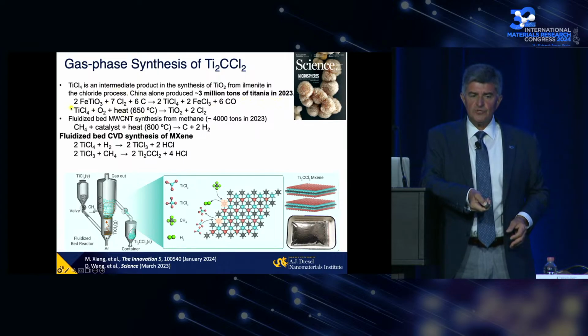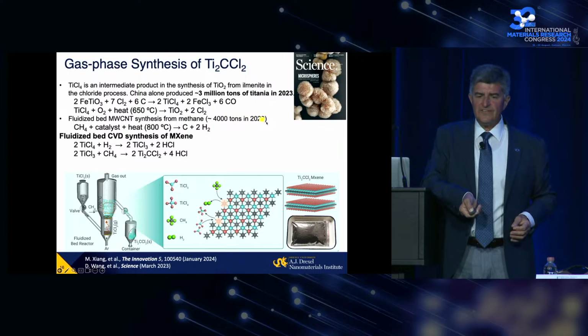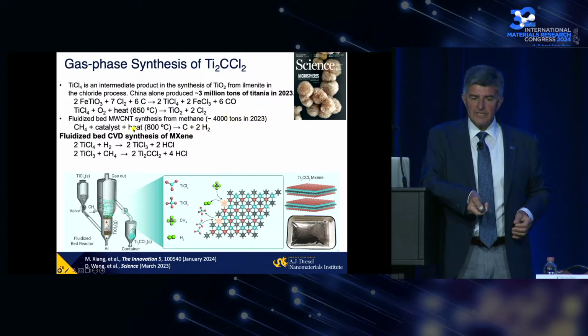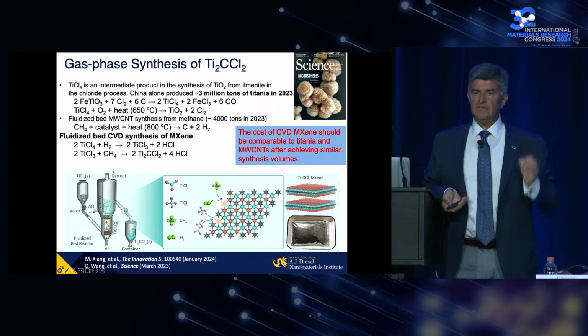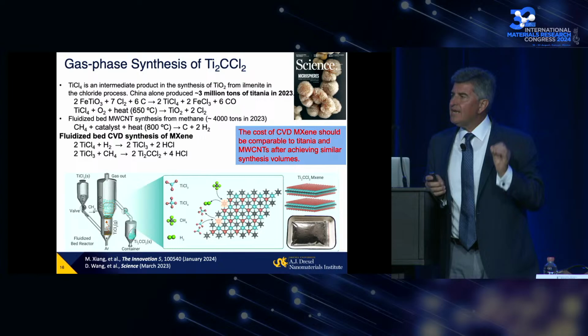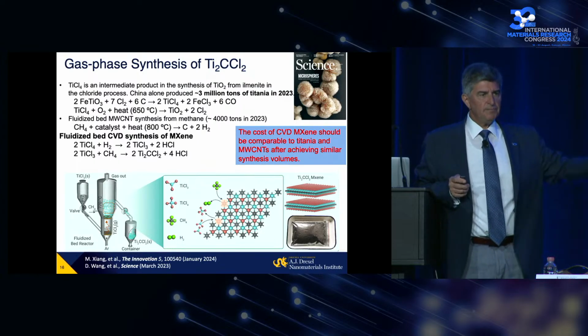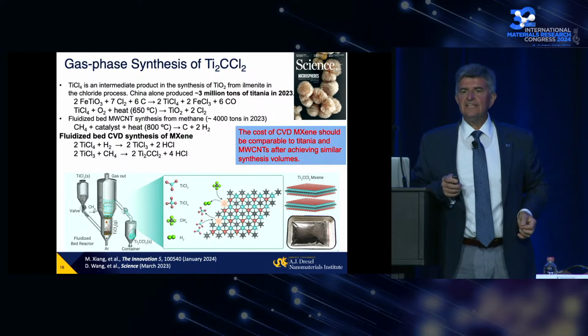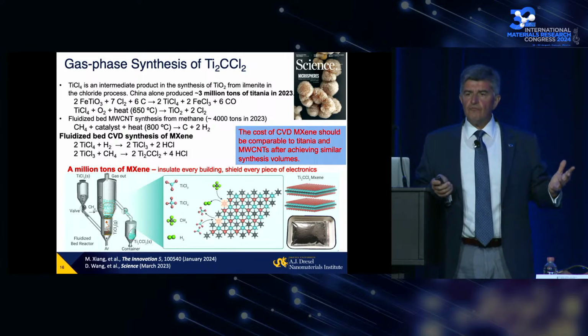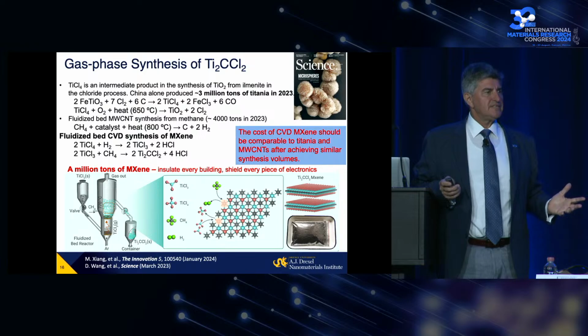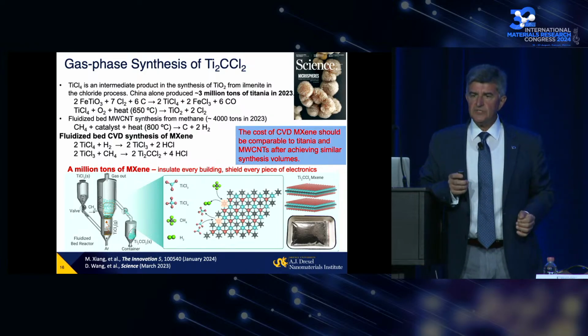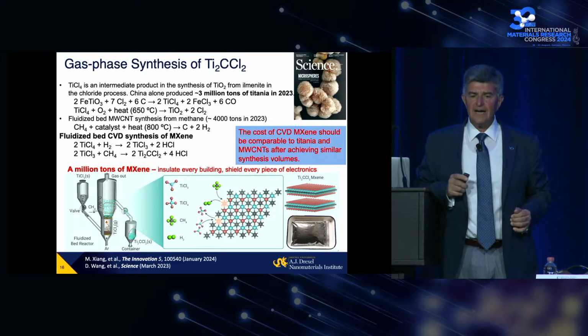At about the same temperature, titanium tetrachloride is mixed with oxygen and heated. Natural gas methane is less expensive. Carbon nanotubes - 4,000 tons were produced in 2023, the ones that go into your cell phones - are produced at even higher temperature than titanium carbide MXene from methane when catalyst is injected. What does it practically mean? We have a process now. We can produce, if necessary, millions of tons of this material, with potentially the cost between multi-wall carbon nanotubes and titanium oxide or titanium. It means that we can really make these materials a major player in technology, from thermal insulation - and I will give you an example - to energy storage and many others.